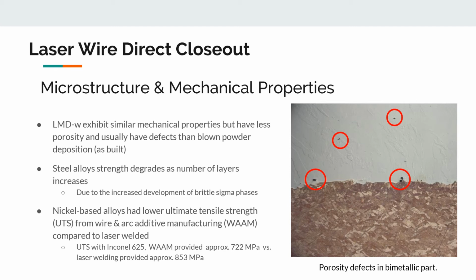With laser metal deposition by wire of steel alloys, there is an increase in brittle sigma phases as the number of layers increases, which degrades the strength of the build, as indicated by the lower ultimate tensile strength of nickel-based alloys from wire & arc additive manufacturing (WAAM). Laser welding generally outperforms laser metal deposition in terms of mechanical properties.